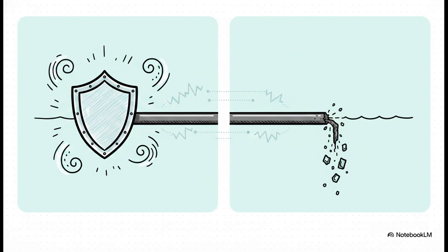The part of the metal above the water, the side with all that oxygen, becomes what chemists call the cathode. In this type of hidden battery, the cathode is the protected zone. It stays totally safe. Meanwhile, the part of the metal sitting just below the water, the oxygen-starved side, becomes the anode. And the anode is the part that takes the hit. It basically sacrifices itself. It dissolves, it rusts, and it corrodes.